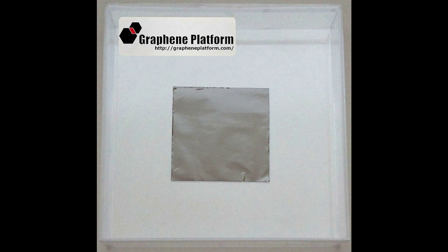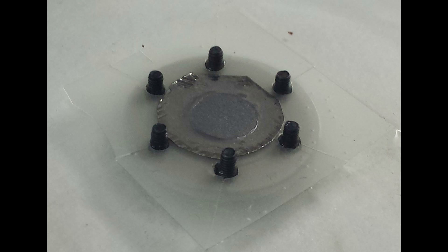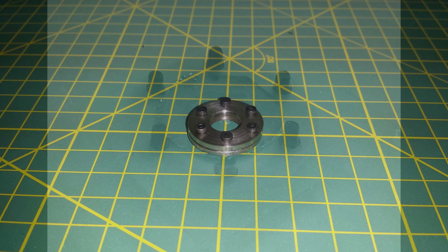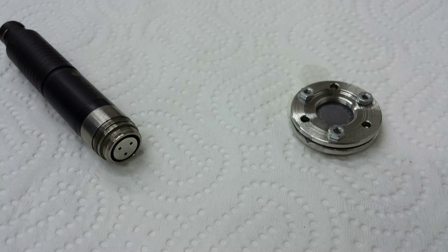The graphene was obtained from commercial multilayer graphene grown on nickel. The nickel was etched away in a chemical etchant, after which the membrane was scooped onto a custom-built plastic holder. The holder with the membrane is then set into a metal ring adapter, tightened to the original housing and attached to the end of an acoustic receiver.